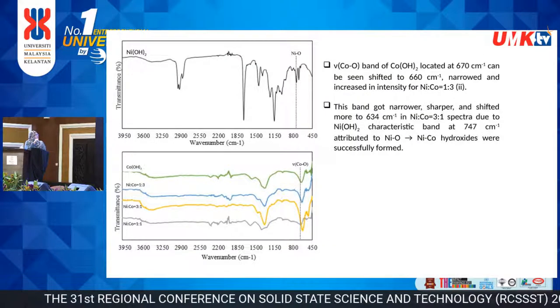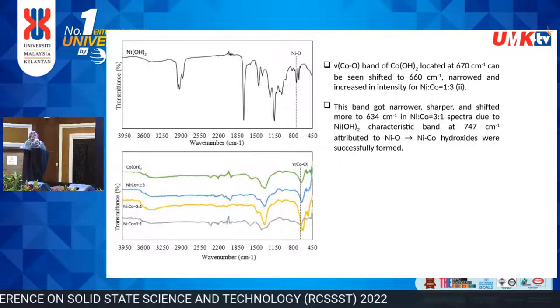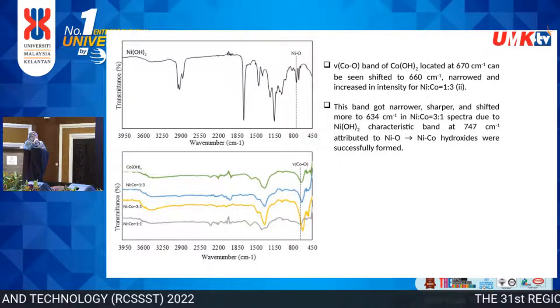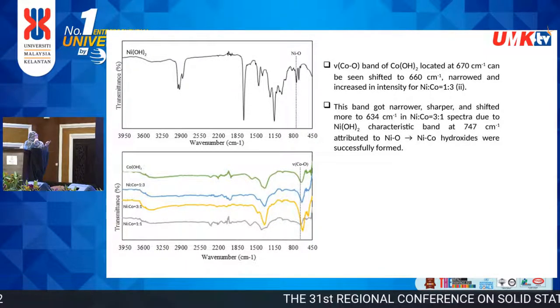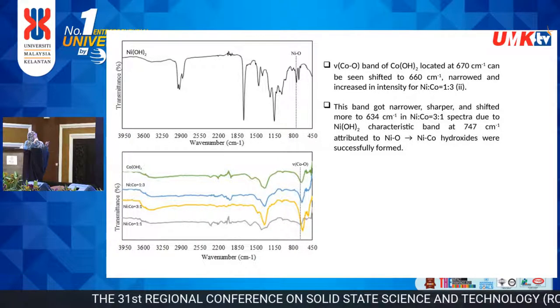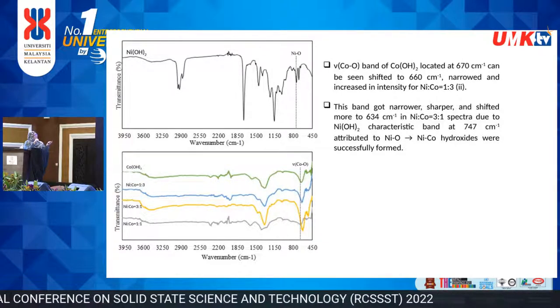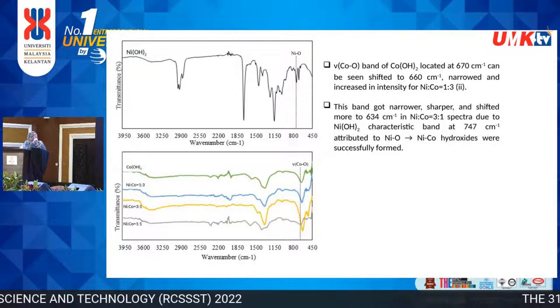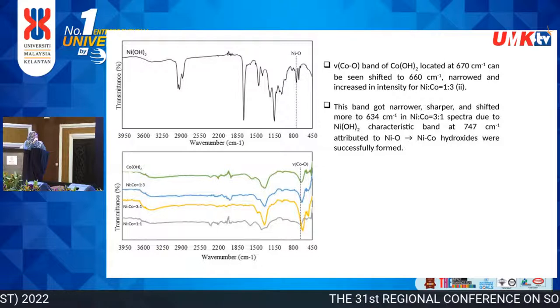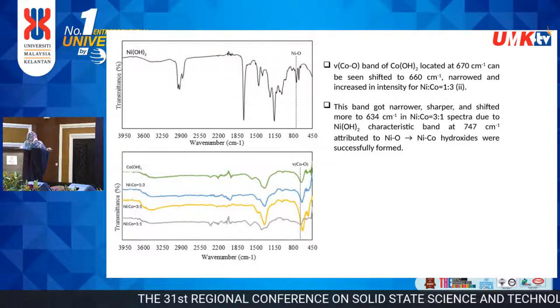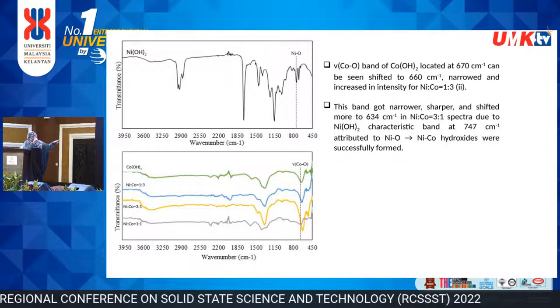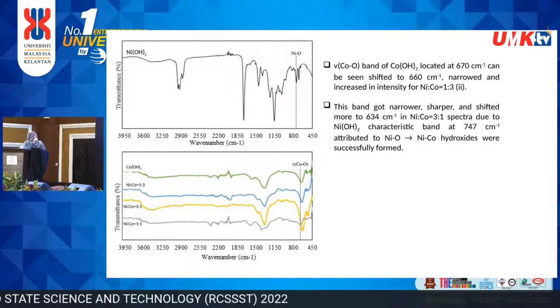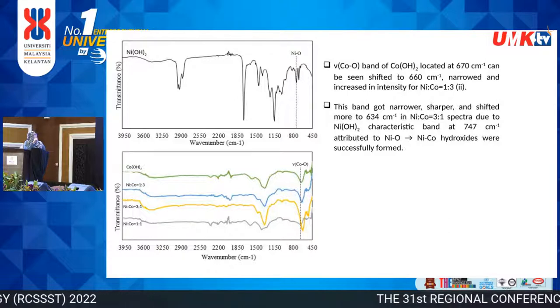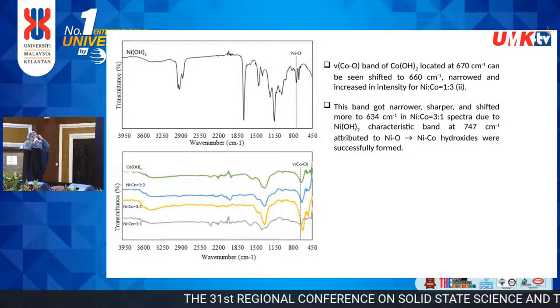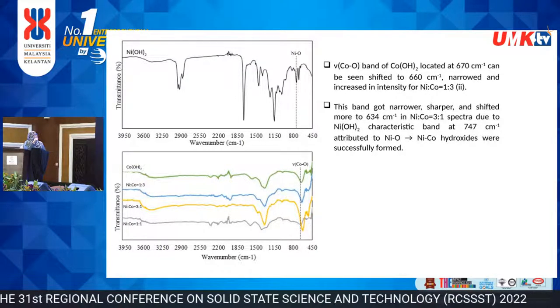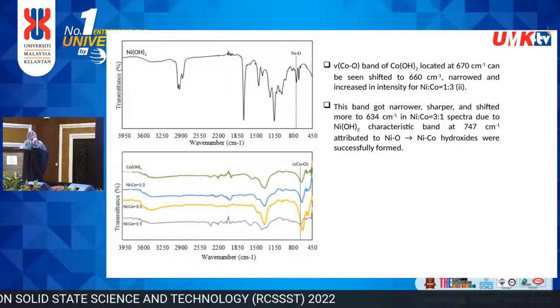This is the FTIR. The upper one is the nickel hydroxide profile, and the green one is the cobalt hydroxide profile. The stretching cobalt oxygen band of cobalt hydroxide located at 670 cm can be seen shifted to 660, the green one, when the nickel cobalt ratio is 1:3. The spectra also show the nickel hydroxide characteristic band at 747, the upper one, attributed to the nickel oxygen band. So this is proof that nickel cobalt hydroxide was successfully formed.